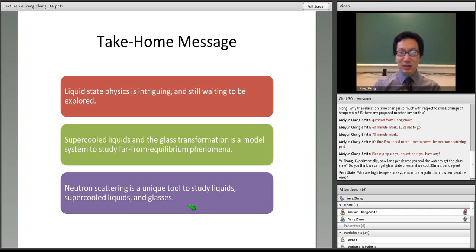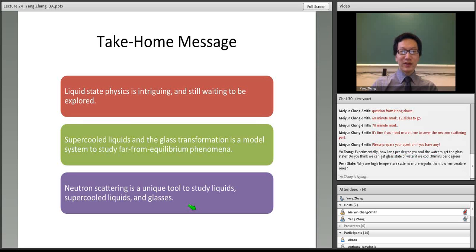The second question is, do you think we can get a glass state of water if we cool 30 minutes per degree? Probably not. At 30 minutes per degree, we can get a supercooled state, but not the glassy state because of the homogeneous nucleation. So unless you cool really, really fast, you won't be able to get the glassy state of water. And it's very difficult. In fact, the true glass transition temperature of water is still a matter of argument.